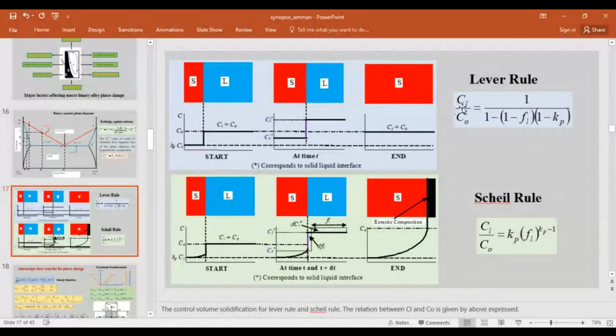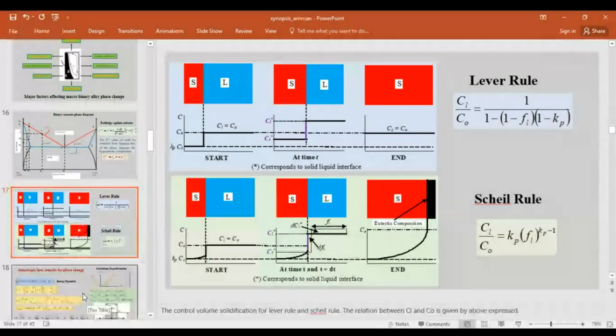Okay, so lever rule is most commonly used because of the simplification, right? And the Scheil rule is there, right? So in the Scheil rule, here we assume the diffusion is to be zero in the case of the solid, which is actually more true, right? So moving on to next slide.